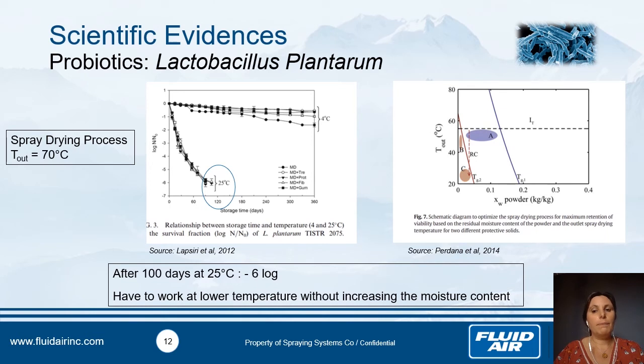Again, Perdana shows that we have to be really careful working with the glass transition when we use sucrose. We can't be higher than, in this case, 75 degrees C, otherwise you have a thermal inactivation. And at the same time, we don't have to be in this part, to avoid the glass transition. So it's very difficult to find the good temperature, lower to not be in this inactivation temperature, and at the same time helping to evaporate water and to reduce the moisture content. So we really think that electrostatic charge helps to give the energy that we can give by the temperature.